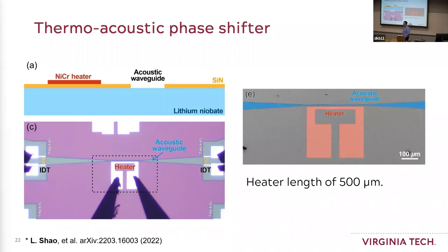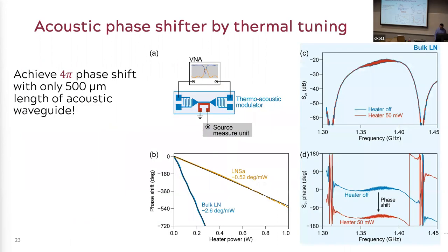This is our cross section. The waveguide you are already familiar with, and we put a heater made of nickel chromium metal. This is our heater, and this is how it looks on the SEM. We apply some voltage on this heater to heat up the waveguide locally. And this is how everything works. We actually applied over 4 pi phase shift using this 500 micron acoustic waveguide. And here is the S parameter at the two ports.